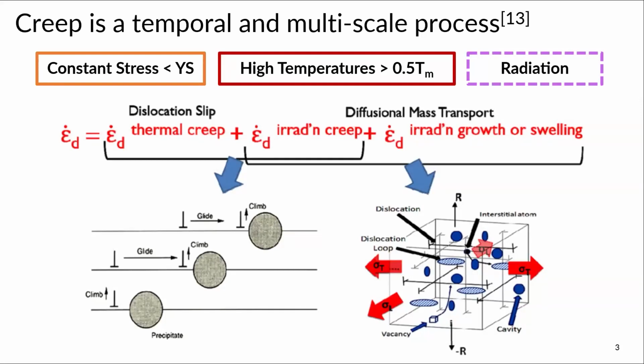In a lot of cases, radiation creep and irradiation swelling are interrelated because radiation introduces point defects, like interstitials and vacancies. And so swelling is this accumulation of vacancies. And so a lot of the time it's hard to deconvolute the contributions from each.